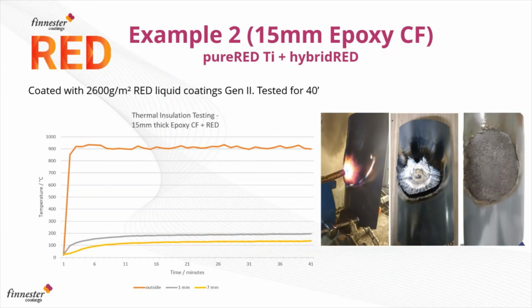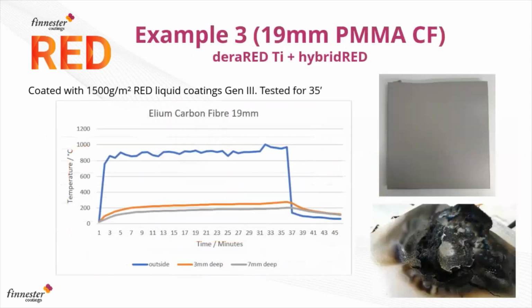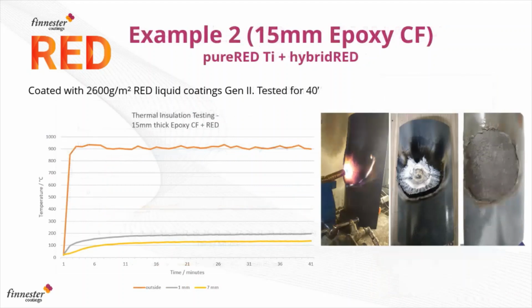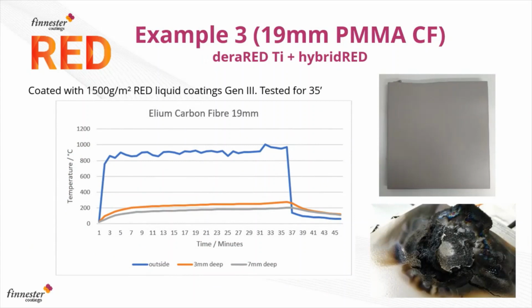Then example 3. Like I said, we have different products. These are the liquid coatings for different applications. If you want to spray or to brush, you can use 2 coatings, which are liquid ones, giving you similar performance. And then we have, let's say, next generation liquid coatings, which will give you similar performance with less thickness. The previous one was 2.6 kilograms per square meter, and the next one is 1500 grams per square meter, with exactly the same kind of performance as the thicker one. And this was done on a PMMA substrate. This is a thermoplastic.